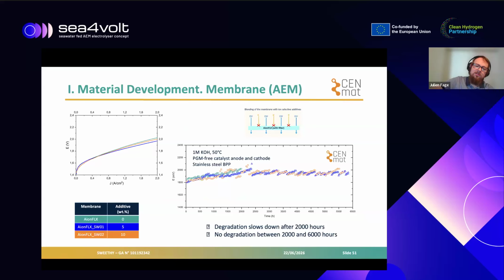If you go to the next slide, I show two different membranes that were additivated with 5 and 10% of filler. In terms of performance, we're in a similar range, around 2 volts at 2 amperes per square centimeter, a little bit below sometimes. What got interesting is that at 2000 hours we had a similar performance curve, but let's leave them running. So now it's 6000 hours running, and what's happening is that from around 2000 to 2500 hours, it stops degrading. So right now we have from 2500 hours to 6000 hours no degradation, which of course is also something that we will bring to the next part of the project when we come to seawater. Longer tests might also be interesting because this is when we see stability.